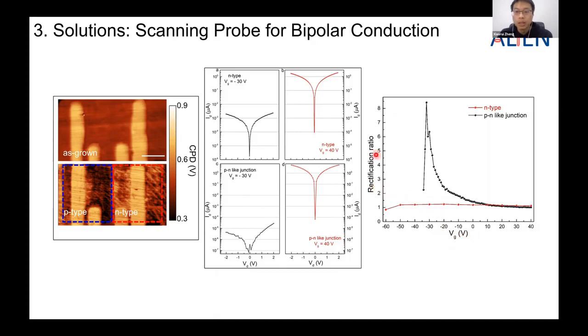So if we plot the rectification ratio as a function of the backgating, we can see for the p-n junction, there is a peak at a certain backgating. So how to understand this phenomenon: in our devices, there are two mechanisms. One is the p-n doping introduced by the scanning probe lithography. The other mechanism is the doping introduced by the gating. The gating is like a kind of universal doping to the entire channel.